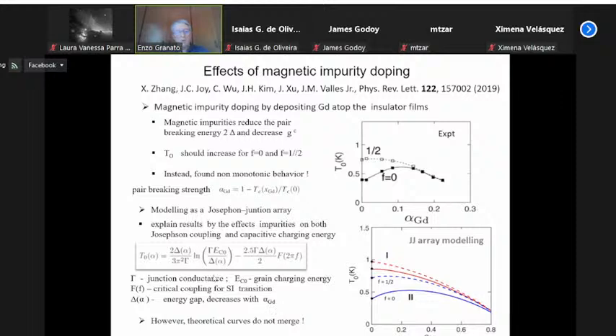And using this model, with some parameters, they were able to find a behavior which resembles the experimental data. Here is the activation energy as a function of the concentration of magnetic impurities for F equal to 0 and F equal to 1/2, and for different samples, which do resemble the experimental data in some way. It has a non-monotonic behavior, but it lacks the merging at some particular point. So the curves do not merge in this particular model.